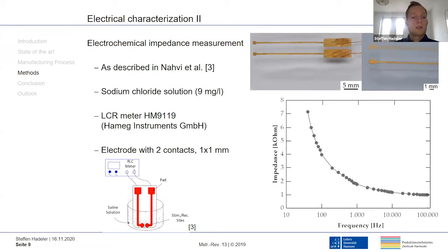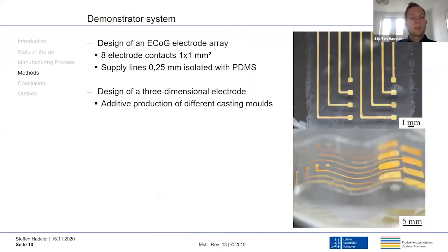With all these results, a demonstrator system should be developed. For this purpose, an ECoG electrode array consisting of 8 electrode contacts was manufactured on PDMS using the developed manufacturing process. And it is shown on the right figure. All 8 electrode contacts are fully functional, and electrochemical impedance measurements have been performed.